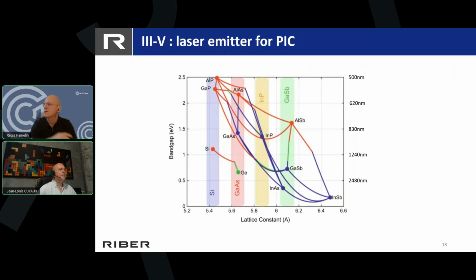Let's go on with the 3-5. This is just to explain the 3-5 here. In the line you see gallium arsenide, indium phosphide, gallium antimonide, which are the main substrates you can buy, and on those substrates you are able to grow with different elements like gallium, aluminum antimonide, or indium arsenide and so on. Different kinds of semiconductors, epitaxy on the substrate. With those stacks you are able to build a specific stack for making, for example, lasers, photodetectors, but also some kinds of electronics. This is really the DNA of Riber.